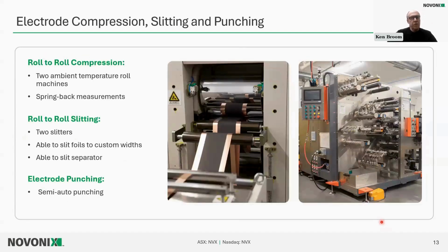So we have 2 ambient temperature roll-to-roll compression machines, and besides checking density as we go along, we can also do measurements like spring back measurement. And this was important in the Mallard Creek polymer situation that I described earlier, because they wanted to make sure that their materials didn't have worse spring back than anything that's already available in the market.